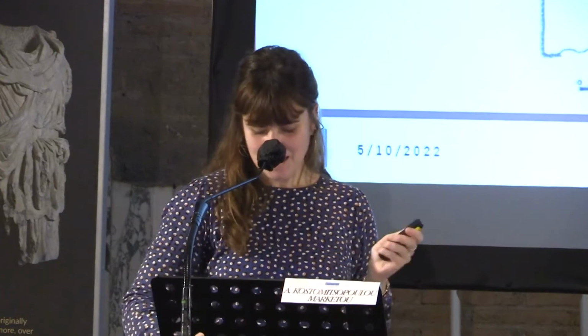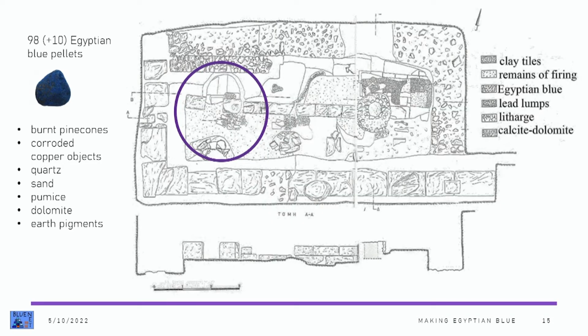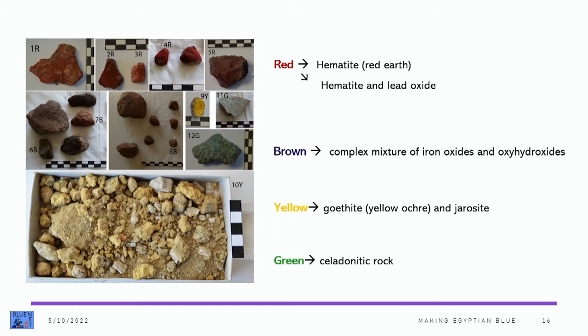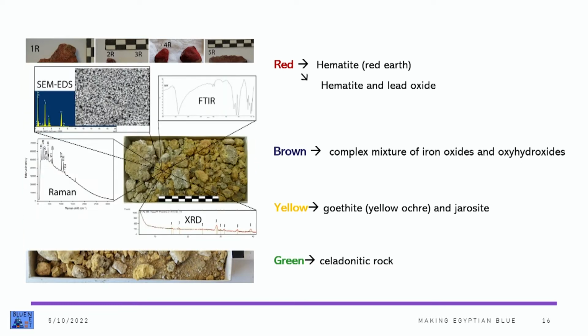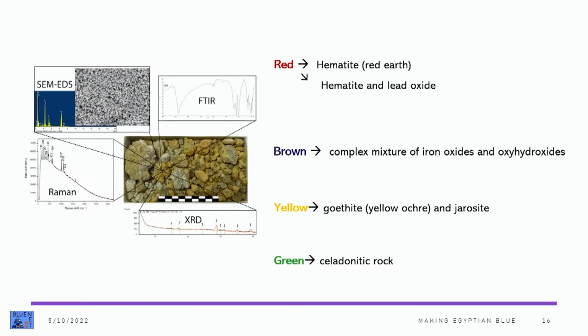Moreover, burnt pine cones, pumice, a white substance that was identified as quartz by chemical analysis, carried out in the 80s, layers of sand, charcoal, dolomite, and also other pigments were found at the site. The other pigments, the so-called earth pigments, have been recently analyzed. The reds are hematite-based and a mixture of hematite and lead oxide. The green was celadonite, and the yellows were both yellow earth, goethite-based and jarosite-based.